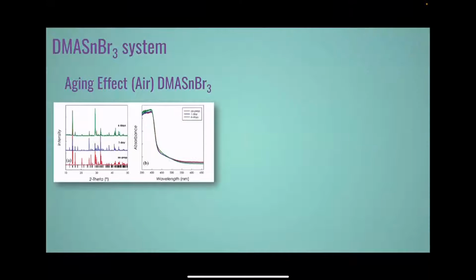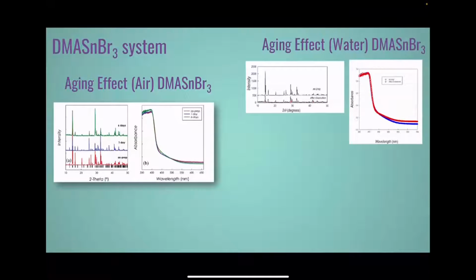So we could observe a good air stability, which was quite an impressive result for a tin-based perovskite, and in general for perovskites, because many of these, also the lead-containing perovskites, if exposed to air, are destroyed, okay? But then we went even further. We put the perovskite in water, and impressively, what we could see is that this perovskite does not dissolve in water. It remained dispersed in water, okay? As a matter of fact, when we recovered the perovskite from water, the diffraction pattern was perfectly as it was as prepared, and also the optical properties were still conserved. So this was quite an impressive result.